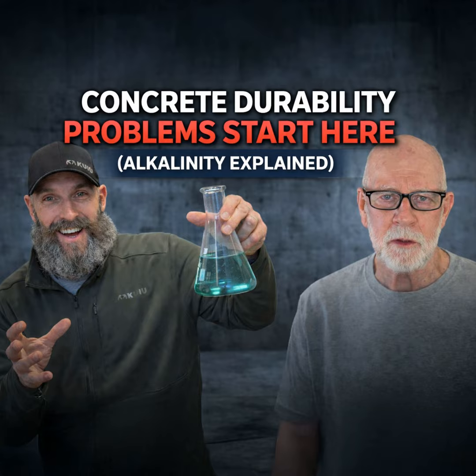Okay, I'm trying to piece this together. So high alkalinity can cause high permeability and high porosity. Yeah, because the cement formation doesn't occur. So what replaces it? Water, because the alkalines capture that water and it's sitting there in place. And if you do a cross-section where this has happened, it's really obvious because the first inch is full of these little holes and pores, and it gradually dissipates as it gets deeper into the concrete.